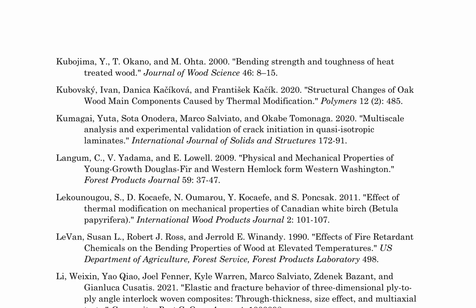A comprehensive review of studies on the thermal modification of wood reveals a multifaceted impact on its physical, mechanical, and fracture properties. Research has demonstrated that heat treatment alters wood's chemical composition, inducing significant changes in its behavior and performance. Studies have employed various heat treatment protocols, including kiln drying, vacuum drying, and superheated steam. Thermal modification processes involve exposure to elevated temperatures, 160 to 230 degrees Celsius, for prolonged durations, influencing the chemical reactions that shape the material's characteristics. Parameters such as treatment duration, temperature, and humidity play a critical role in determining the outcomes of the process.